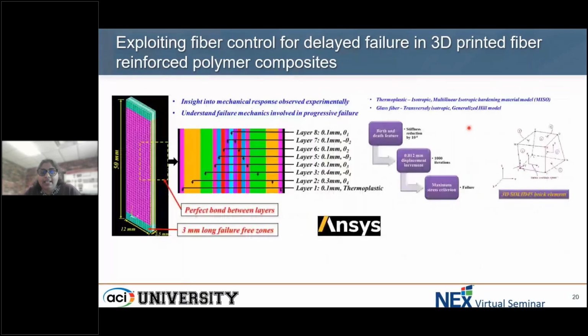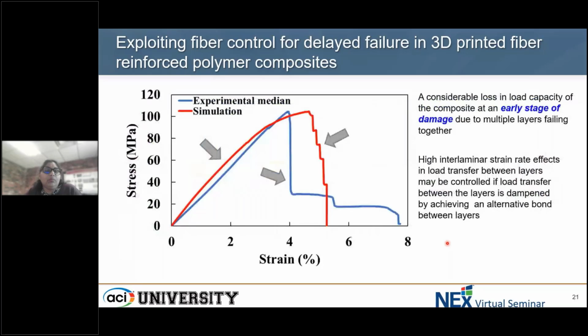For that, we performed some finite element analysis. We used ANSYS modeling, and we assumed a perfect bond between layers, which in all reality is not possible. So once you get that perfect bond between layers, the same exact design behaved somewhat differently than the original. You can clearly see there was no longer an abrupt failure. There was no longer a large drop in capacity. There were more smaller drops in capacity, which is more of that progressive kind of failure that we've seen in the past. So a considerable loss in load capacity of the composite, if you see in the experimental, it's because of an early stage of damage due to multiple layers failing together. So because of those multiple layers failing together due to the bond that is between those layers, you see that because of a perfect bond, that is not the case that is happening here.